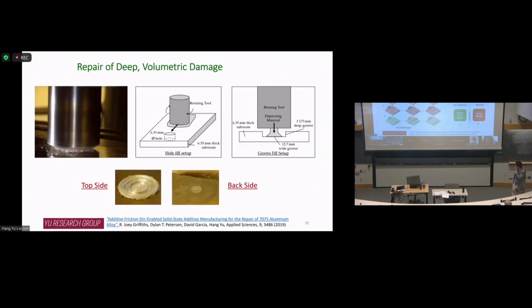So here's an example. I don't know if you can see this, but this is a hole, a through-thickness hole in a 1/4 inch aluminum alloy plate. Our process demonstrates that you can deposit material into the hole. Not just deposit material, essentially you're pushing the material into the hole. There's going to be mixing and interaction between the deposited material and the sidewall. By doing this, you can get a good interface bonding. And we show that for a 1/4 inch thick plate with a through-thickness hole, we can fully fill that. You can see the backside, the material is fully filled.